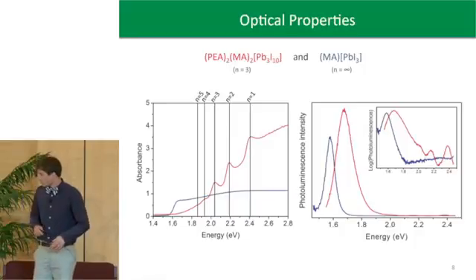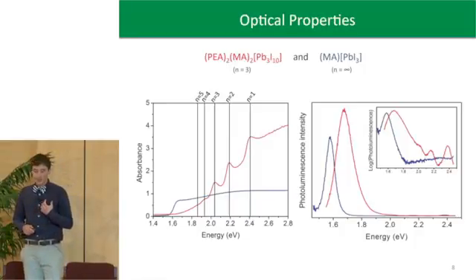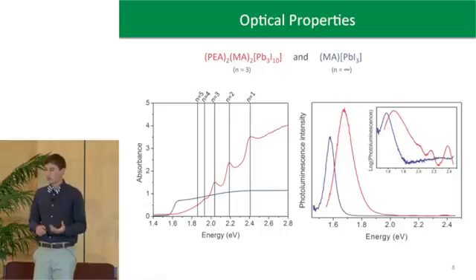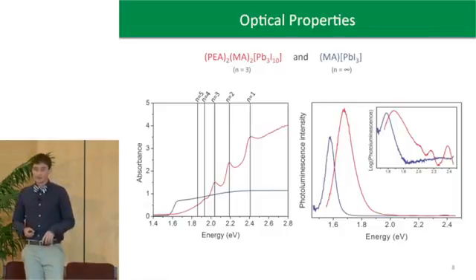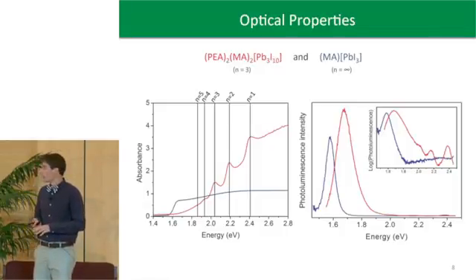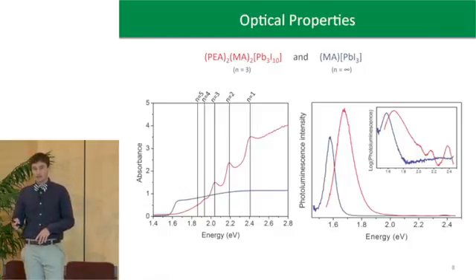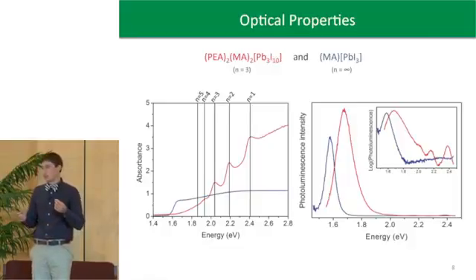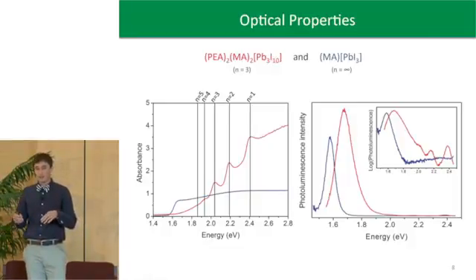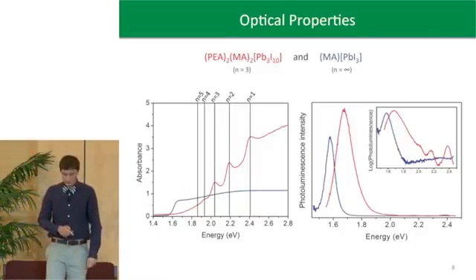In my material, the photoluminescence occurs at a slightly higher energy, around 1.7. This is significant because you're getting a higher energy photoluminescence, which is what you would expect from a higher bandgap material. However, this photoluminescence is not actually occurring from the N=3 material in the film. So we think this is actually a lower energy material in the film where all the carriers are collecting, and then photoluminescence is occurring from that material.